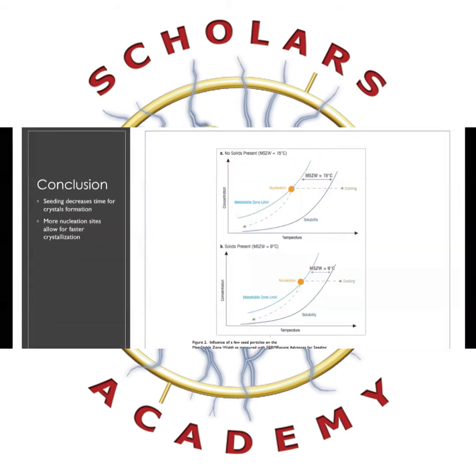So here on the right-hand side, we can see data taken from an MIT experiment in which the data is for an inorganic compound being crystallized from water. Now, cooling is at a fixed linear rate, and figure 2a shows an MSZW of 15 degrees Celsius when cooling a perfectly clean particle-free solution.